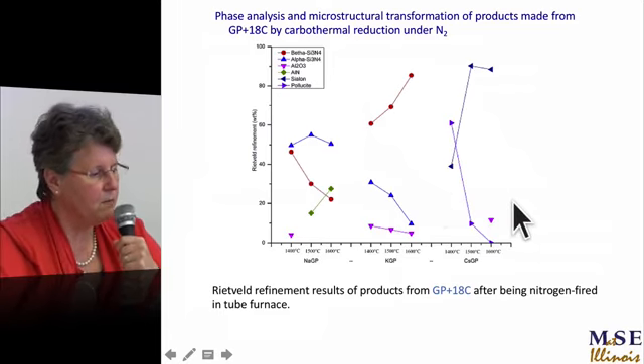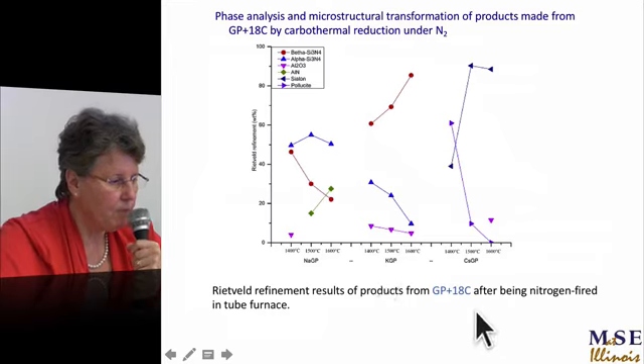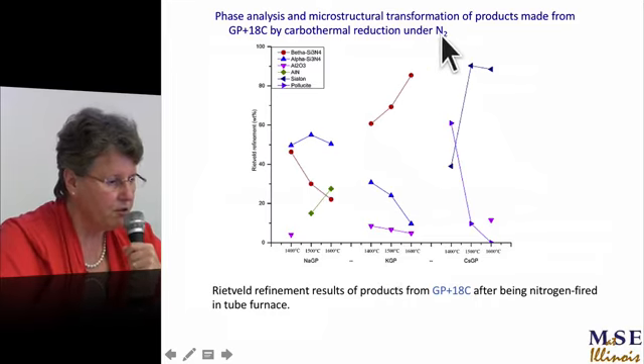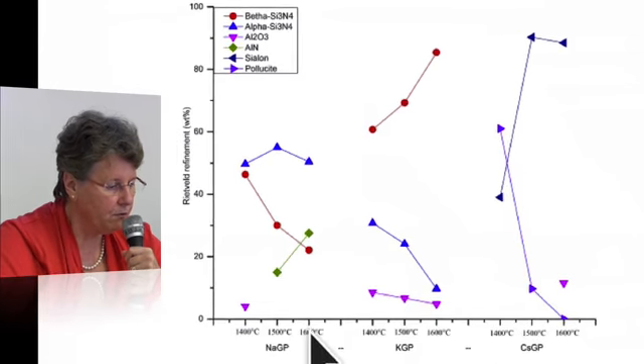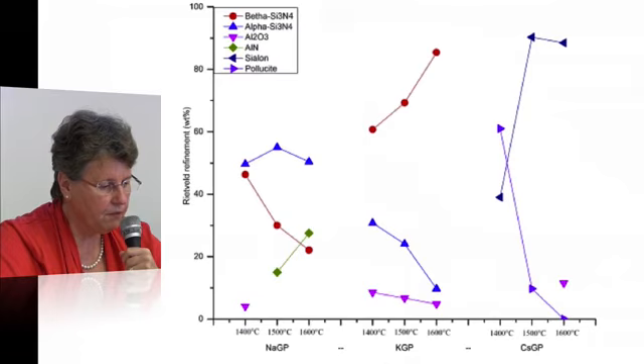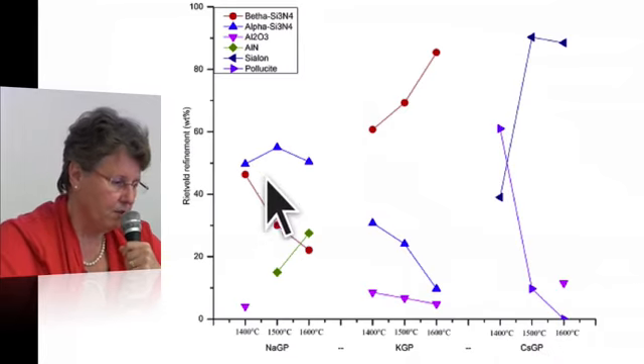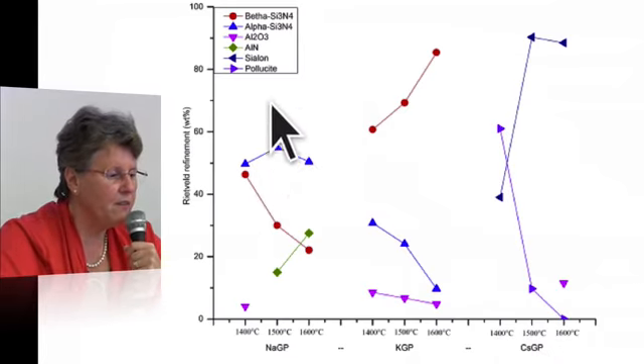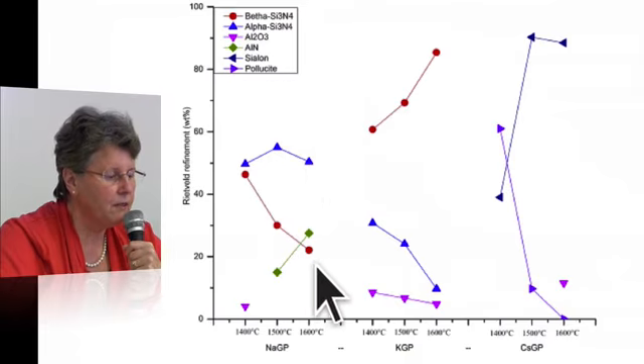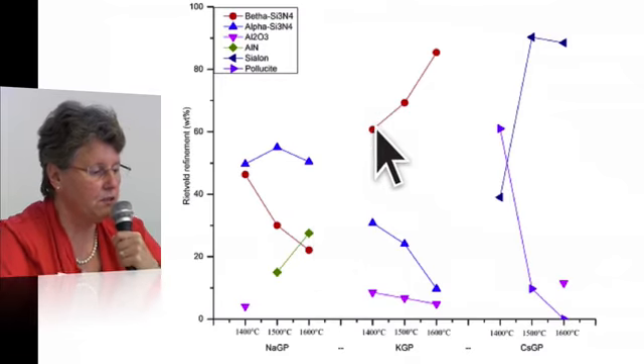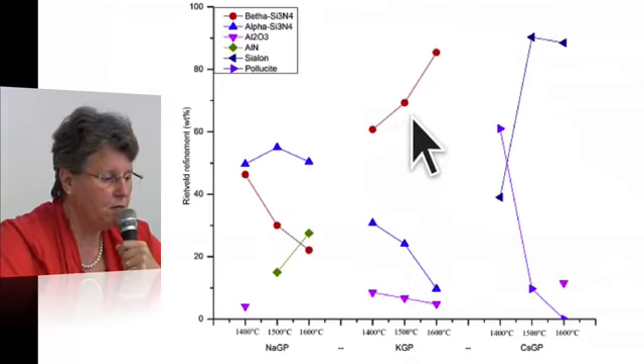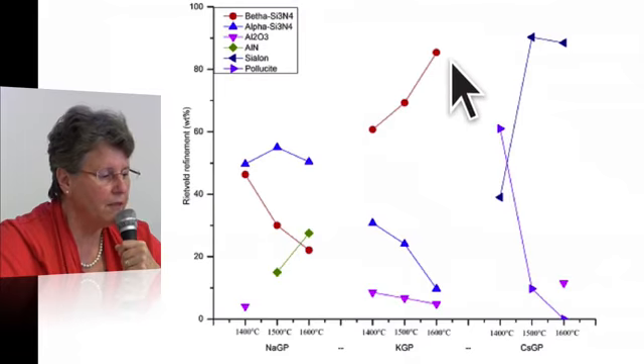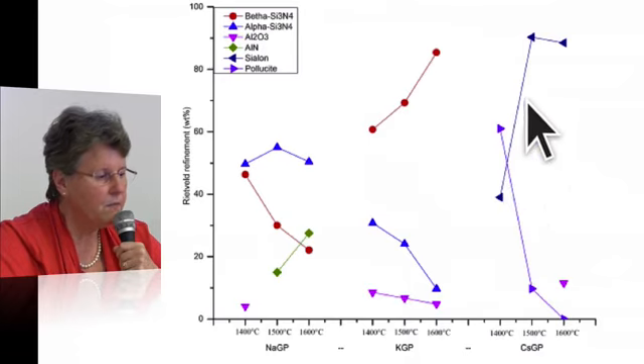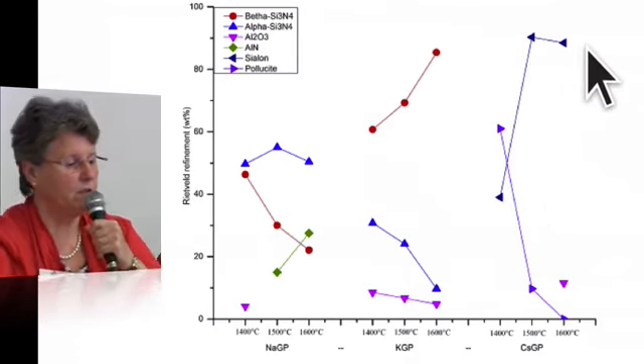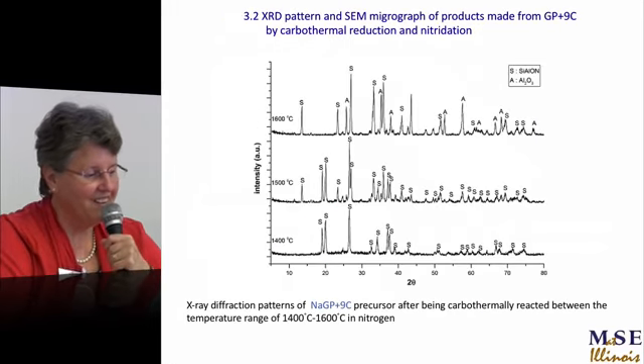So this is a bit of a summary about how you add carbon, but you do it in nitrogen. Here's the nitrogen and you add carbon. You do 1400, 1500, 1600 with sodium, 1400, 1500, 1600 with potassium, 1400, 1500, 1600 with cesium, for 2 hours. And so here you'd form alpha silicon nitride and less beta, and a bit of aluminum nitride. Here with potassium, the predominant phase is always beta silicon nitride, and here with cesium, you'd make alpha silicon nitride. So that's good to know.